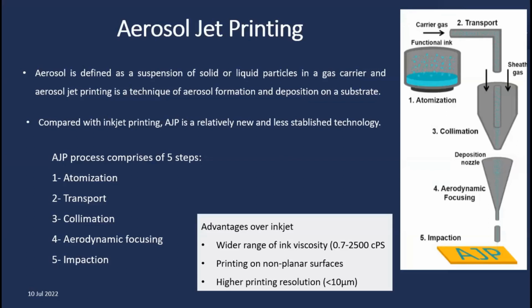And that's where I think the aerosol jet, which is from Optomec, came into the picture. What they did was they can now fairly change the distance between your printhead and your substrate. And the idea here was that anything that can be made into an aerosol, which is a formation of droplets of a material, you can basically print it with this printing technique. The way it functions is that you take your material and then you form aerosol droplets of this material. And this is carried, so you transport this material in a system where all these droplets, the cloud that you are forming, is basically collimated into a stream.